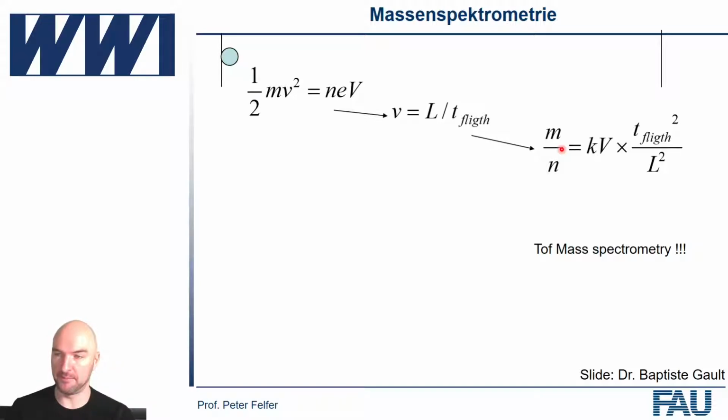A good example is if you have a molecule evaporating, say O2: O2 2+ versus O+. In principle, there's no way to distinguish that without knowing what the ion energy is. And this might be a very large contribution to why oxygen stoichiometries in oxides are not reproduced very well.